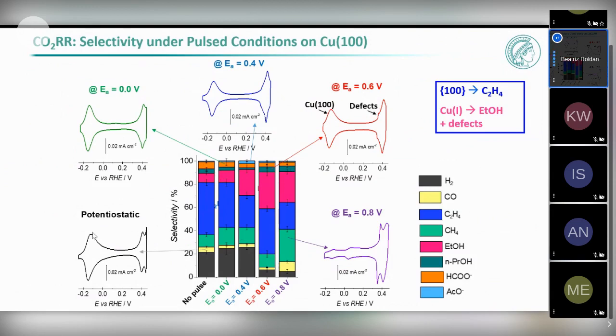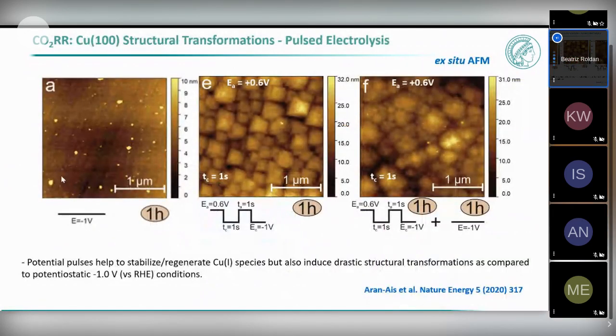At the same time, if you follow the evolution of the CVs, you can see that they are also changing. So here, for example, this feature is typical of the 100 facets, and when we go further in the oxidative regime of the pulses, we can see the formation of defects. So the structure is changing. So we can follow this. You can do atomic force microscopy. And when you run this reaction for 1 hour on a copper 100 surface, you see here the surface looks very flat. So not much changes. But if you apply the pulses, you see these massive reconstructions. Still, there is some order, but it's very, very rough. And actually, you see the formation of this type of pyramidal structures.